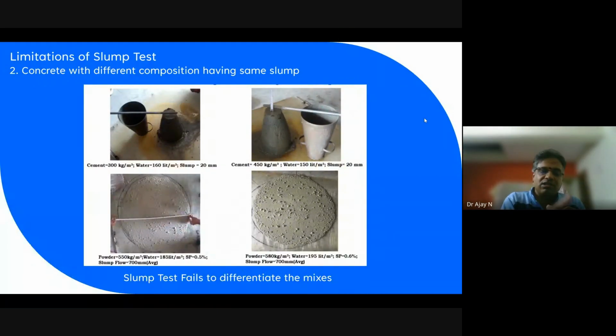Abrams' law, what we say is the universal law, water cement ratio versus strength. When we increase the water cement ratio, the strength gets reduced. So when we increase the water cement ratio, automatically the slump also gets increased, because of the frictional force between the aggregates. The binder material, the cement and fine aggregate, is acting as a binder material and a coating material for the aggregate. It is acting as a lubricant mainly.